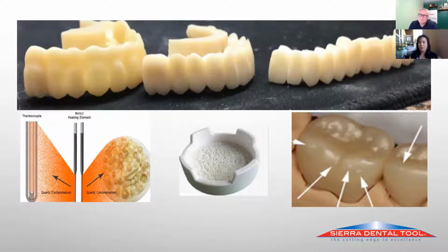A lot of times people will call and say there's something wrong with my zirconia. There's absolutely nothing wrong with the zirconia. That's actually the quartz. You put your crown into the tray, occlusal side down to sinter. The quartz that was already in that tray is melting into the zirconia. If you grind on those little white spots, they'll actually open up and it'll be all airy and porous inside, like a white powder will come out, and that is quartz.